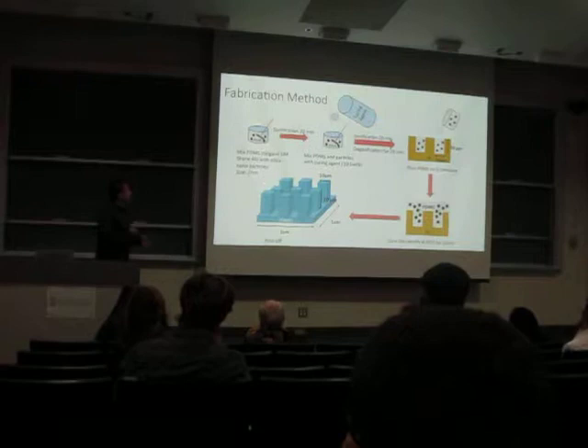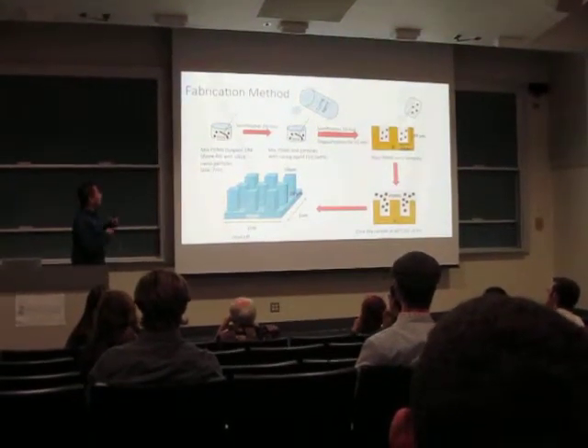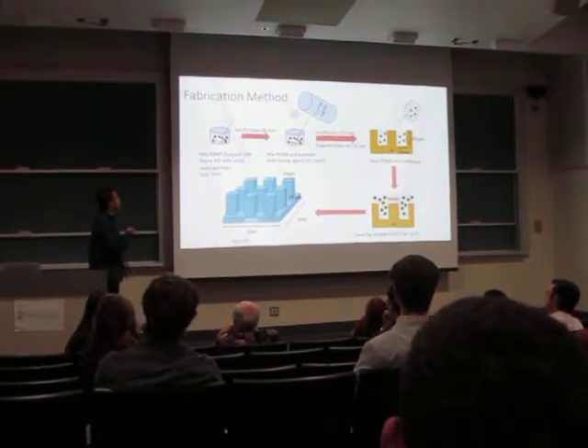So here is the fabrication method. Remember I was telling you there are two methods: one is adding particles, and one is increasing the curing agent. If we want to add particles, we add them in the beginning. If we're just increasing the curing agent, we don't add particles at the start, but everything else is the same.